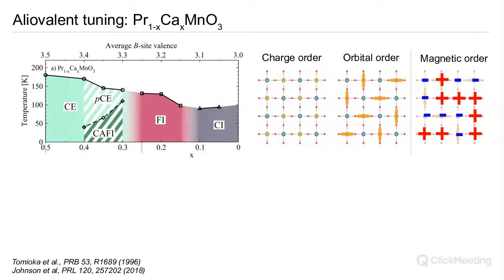So we can just focus on the half-doped end here, the so-called CE magnetic phase. And I've just drawn diagrammatically what happens in the material. We get a charge ordering at the B sites. The oxidation state is normally +3.5. It segregates into 3+ and 4+. This is then accompanied by some orbital ordering, where the 3+ ions have a Jahn-Teller instability that I show with this single 3z² minus r² orbital in the figure. And then we have this complex extended zigzag type magnetic order at low temperature.